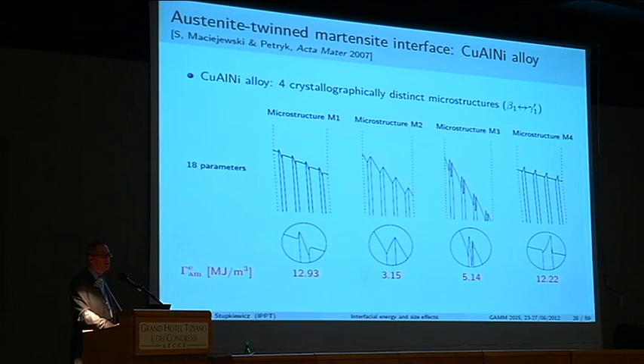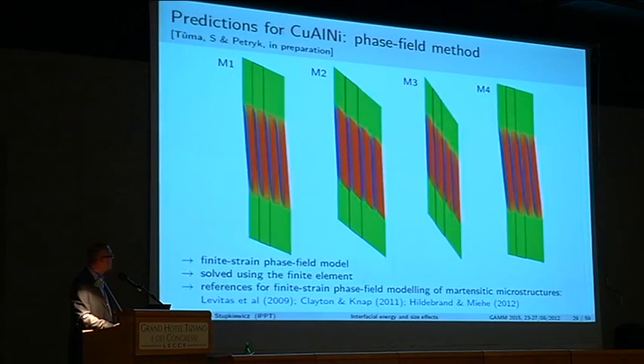And not much more to say about it, but as I told you, we have now these new tools like phase field modeling, so we have tried to do the same thing using phase field modeling, and here is the result. So we have the four microstructures and the four unit cells, four microstructures obtained from phase field modeling. So the green is the austenite, and blue and red are the two variants of martensite. Here we use a finite strain phase field model, and we solve the problem by finite element method.